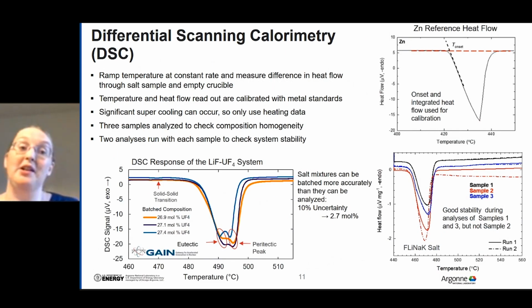I'll move on to differential scanning calorimetry, which is what we use to measure phase transition temperatures and heat capacity. So the general idea is that you ramp temperature at a constant rate and measure the difference in heat flow between your salt sample and an empty crucible. We do calibrate our temperature and heat flow readouts with metal standards. You can see an example of that in the top figure here, where we measured zinc. The intersection of those red and black dashed lines gives us the melting temperature, so we can calibrate that against a known value, and then you integrate the area of that curve to calibrate the heat flow of the instrument.